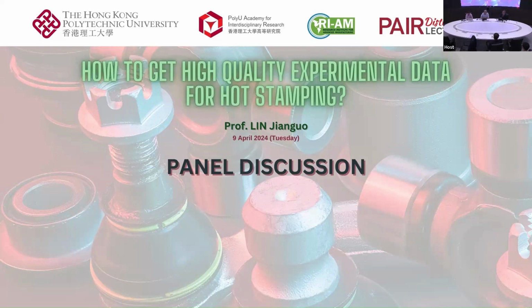I have a question about your tensile test data. So you are trying to tell us that you get two curves, one going up, one almost flattened, and then you say that the flattened one should be the real data. But my question is, because it's a tensile test, if you get a flattened true stress, that means in the force transducer you will get a reduction of the force. When you do tension, the cross-section area is reducing, so you will get a reduction of the force. But can you show us some evidence of the reduction of the force?